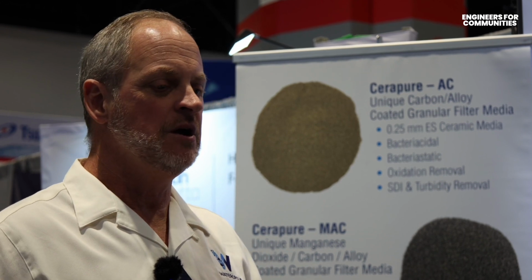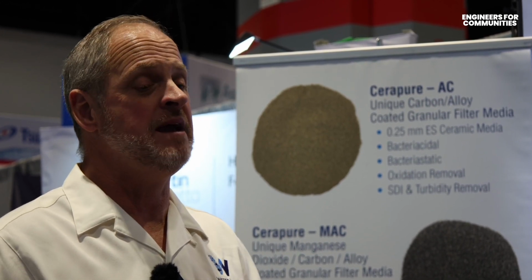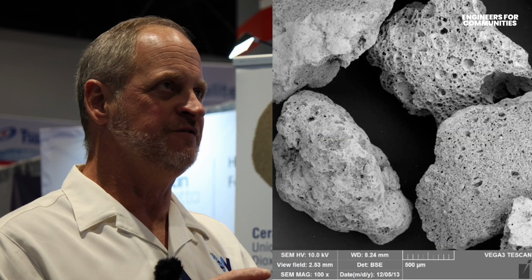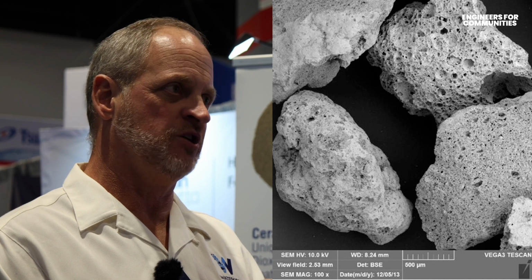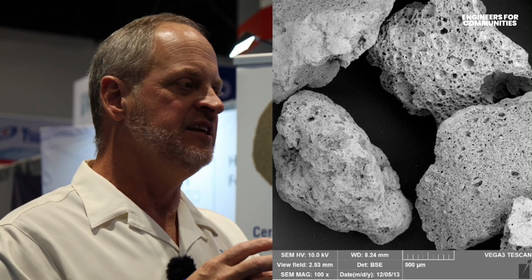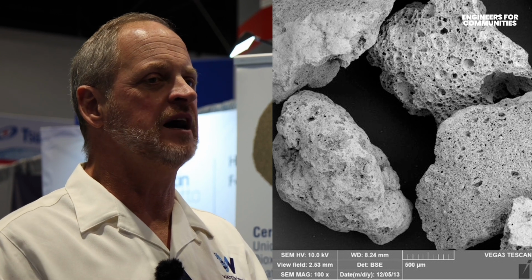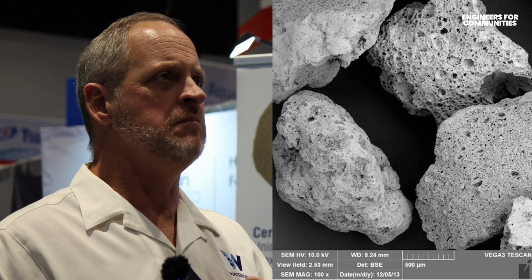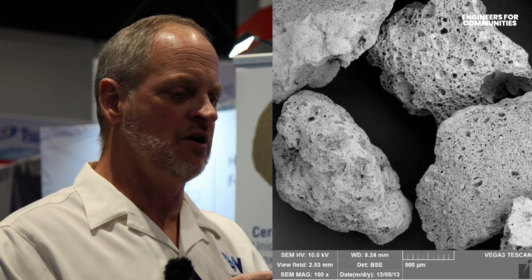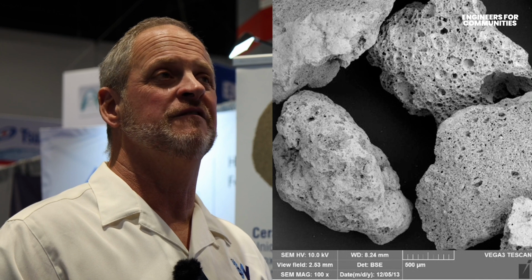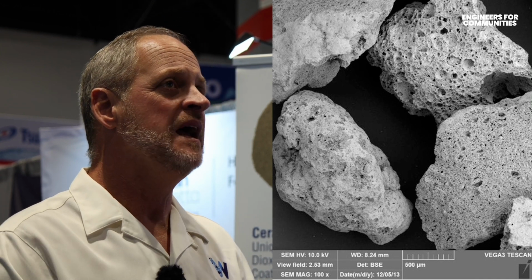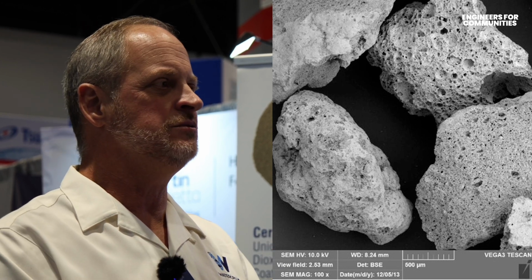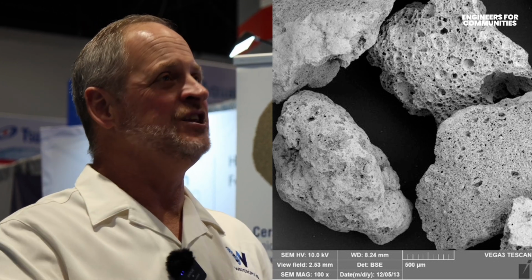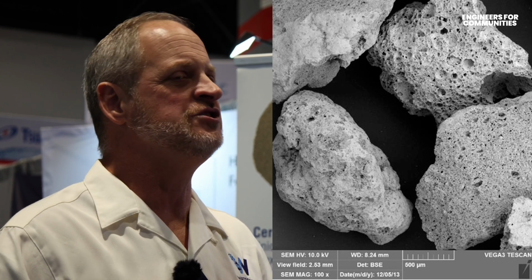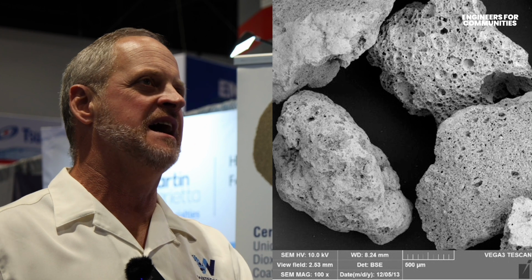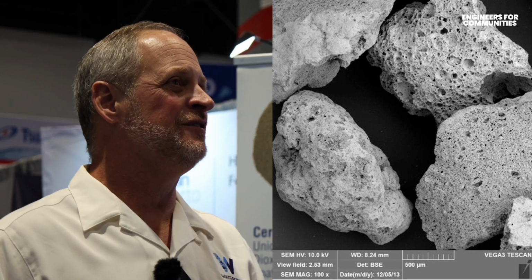And in those situations, we want a high surface area. So we actually make expanded clay materials, which have immense surface area and are a good host superstructure for biological growth. And in those situations, particularly in warmer waters where you've got high DOC, some good alkalinity, and a modest pH, you can get robust biological growth that ends up consuming the iron and manganese as part of the digestive process of that microbe. And then you start growing microbes in the bed. It starts to add to head loss, and periodically you backwash the filter and you knock off that excess biological growth. It's usually in the form of some extra polymeric substance, EPS. So it's the slimy goo that sets up in a filter.